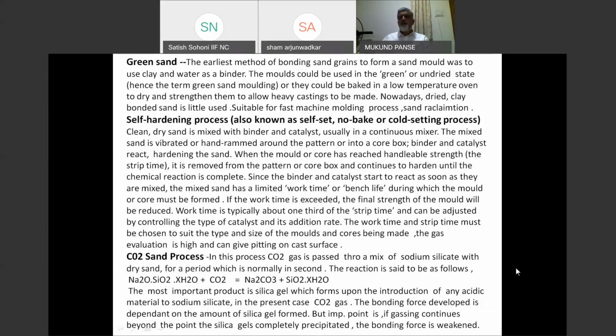Dry sand was used earlier, in which the same sand with some small amount of core oil, fire clay and iron oxide was used, but I think probably nobody is using it now because no-bake and CO2 sands have become quite common. But green sand has its own advantages. Its collapsibility is very good and it is still used by many foundries, especially where machine molding is used or for very small castings where not very stringent requirements are to be met. It can be comfortably painted with spray painting, and you get a fairly good surface finish as well.